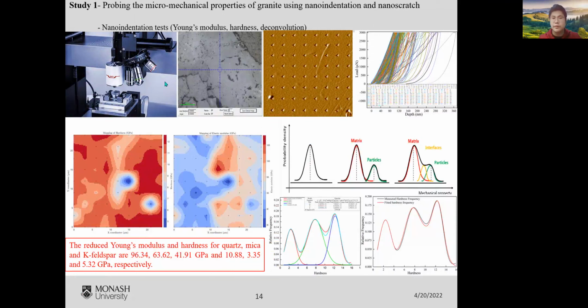There is an optical microscope in the nano-indenter, and we use this optical microscope to locate the area that we are interested in. After the relocation, we can carry out the grid nano-indentation test, and from this indentation test, the load versus displacement curve can be extracted, and according to this curve, both Young's modulus and hardness maps can be extracted directly. Because our granite sample is a heterogeneous material, which means it's composed of multiple phases, a deconvolution method has been adopted to extract the reduced Young's modulus and hardness of each single phase.